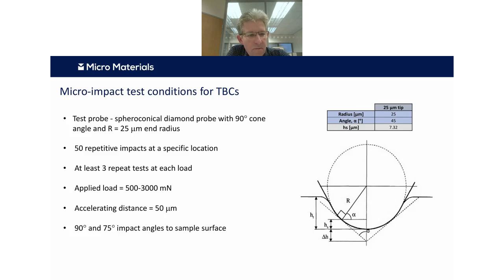Then we did some micro impact tests on these two different coatings with, in this case, 50 impacts at the same location, and repeated this test 3 times over a range of different test loads, accelerating over 50 microns. We did these tests at 2 different impact angles. The spherical probe has the geometry shown on the right: a 25 micron end radius going into a 90-degree cone angle, with a transition between the spherical part and the conical part after about 7 microns penetration.